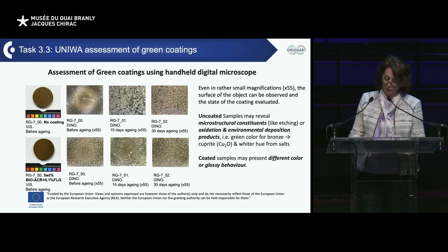Handheld digital microscopy can prove to be very helpful in the examination of the surface and the coating of metal surfaces. While visible inspection can record the object's surface, usually coatings are colorless and transparent. They could potentially be located in the rare cases where coatings are not evenly distributed, and differences of morphology between metal surface and coating surface can be observed. Therefore, closer inspection provided by the handheld digital microscope can be of assistance. Uncoated areas reveal microstructure constituents like etching, surface oxidation, for example, the green color of patina, and environmental deposition, for example, whiter hue from salts. Coated areas may present different color or glossy behavior.